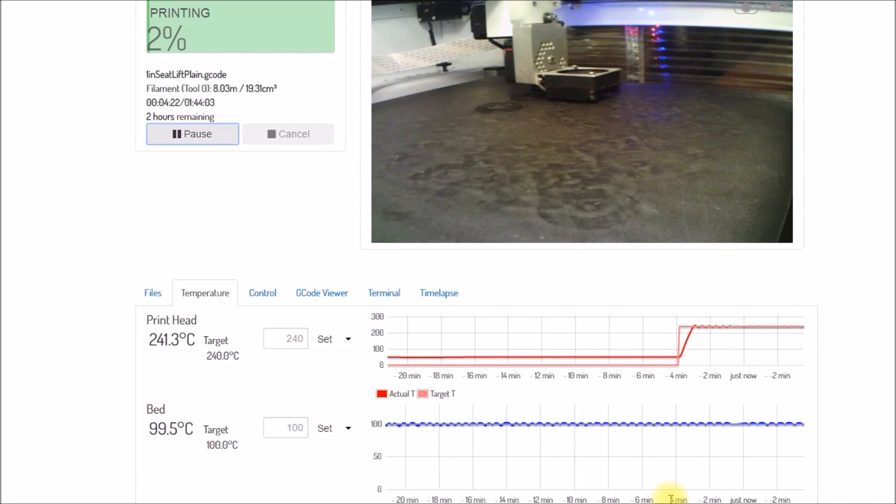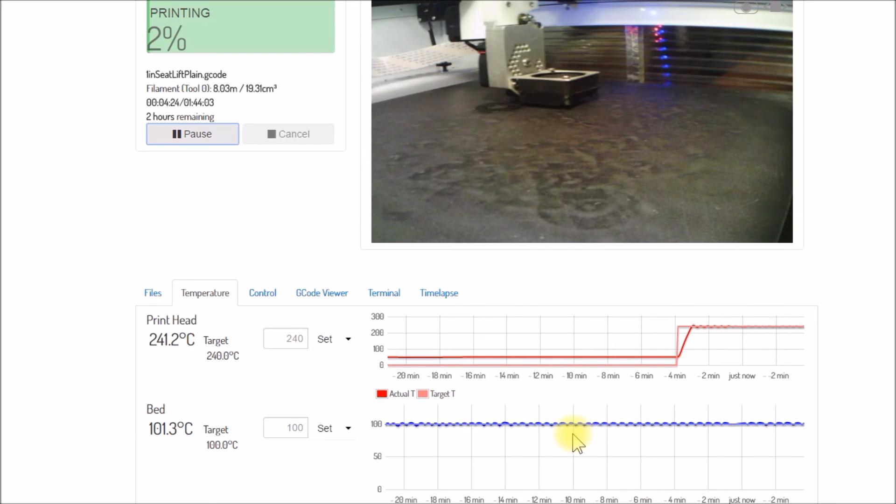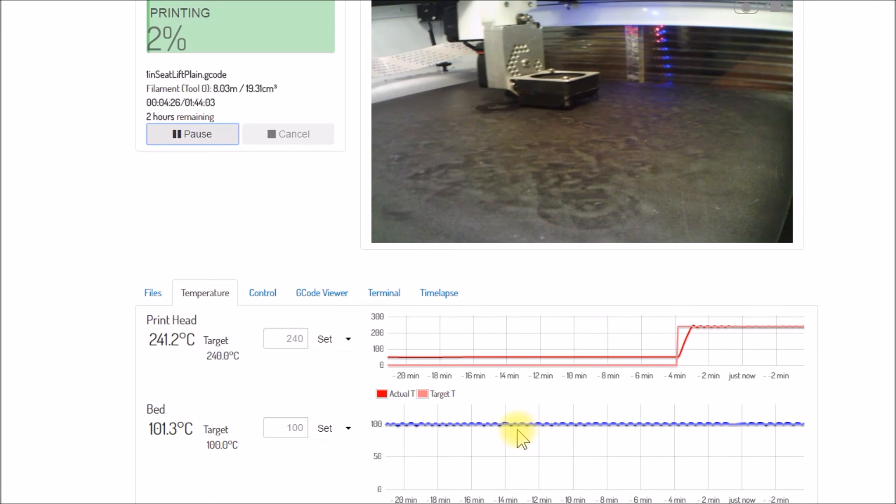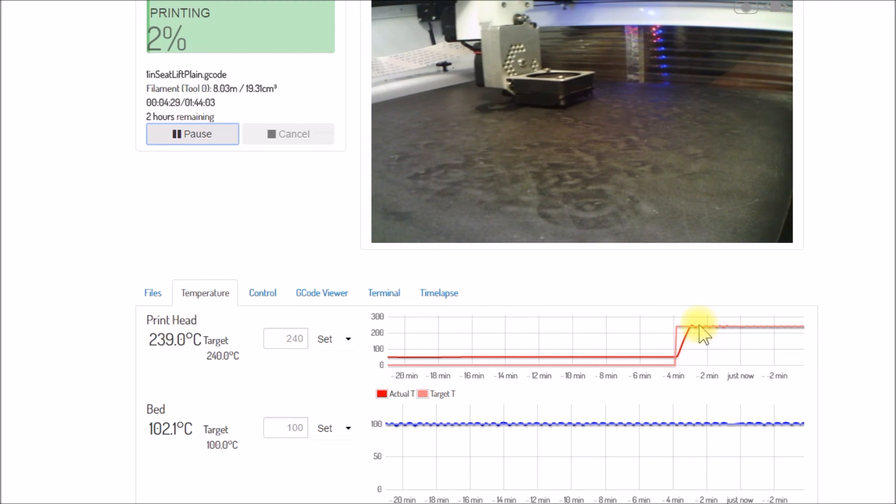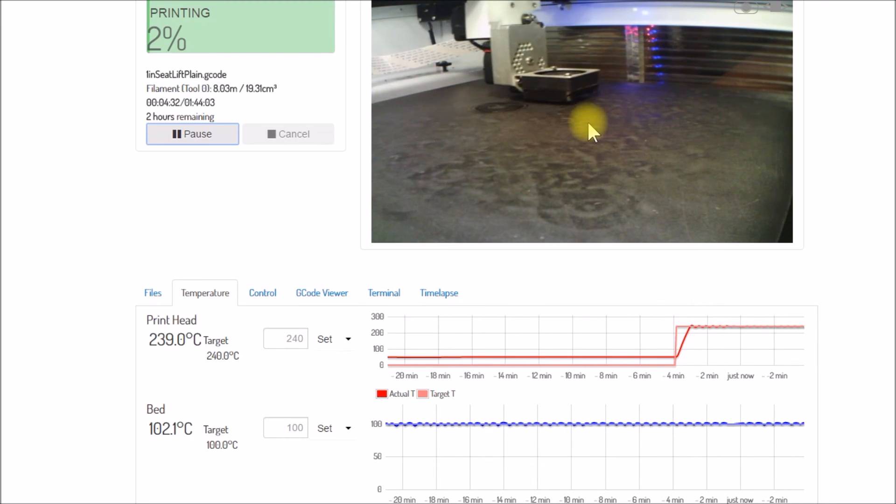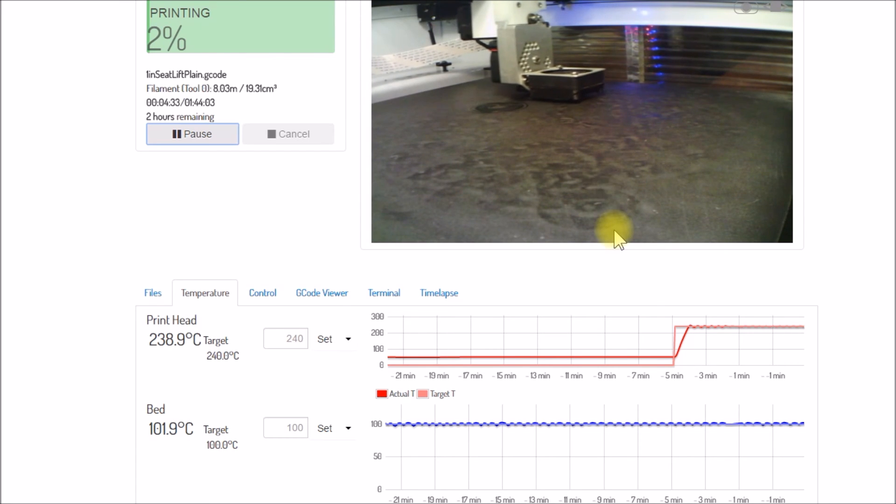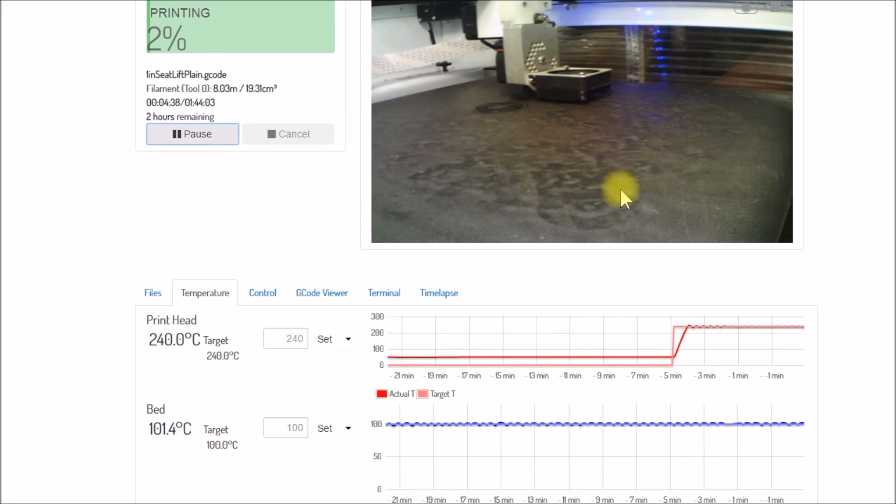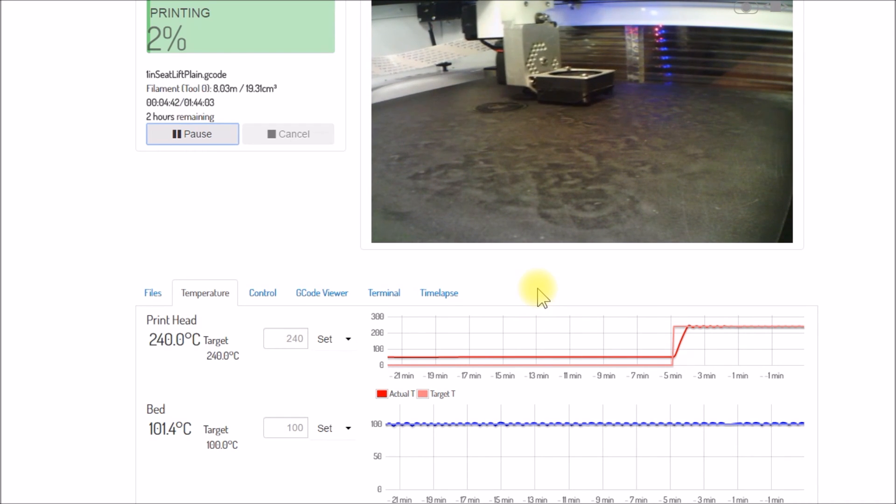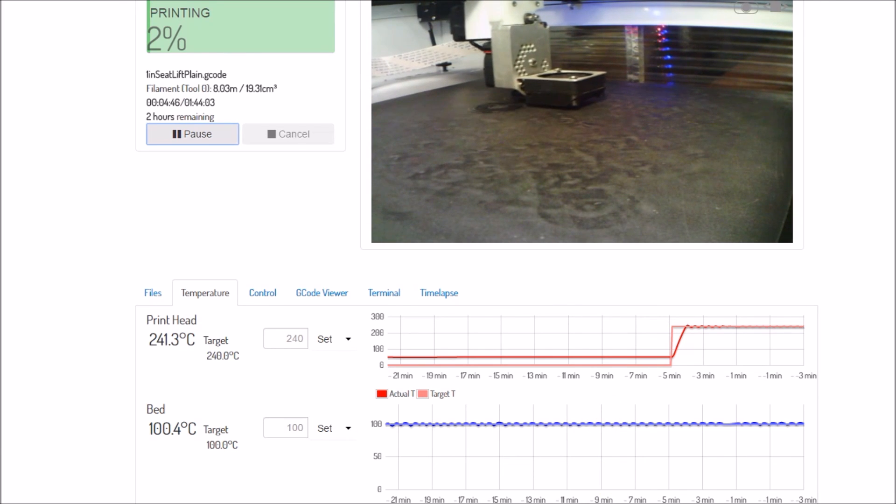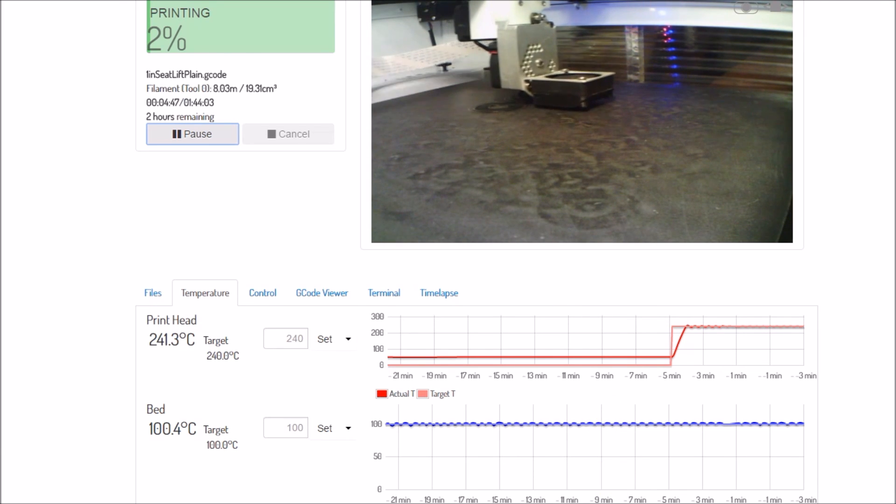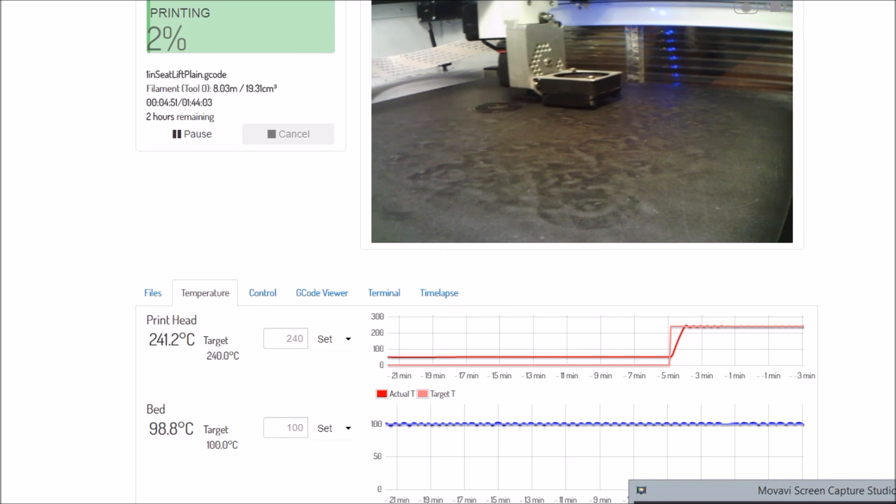So there's my printing process with ABS on BuildTak. The key is I heat the bed up, make sure it's hot for about 10 minutes, then I heat up the extruder for a minute or two, then I start my print and just check it for the first couple of minutes, make sure everything's working there. And once it is, I am done and I just let the printer go and I go do something else. So that is the way I work with that.